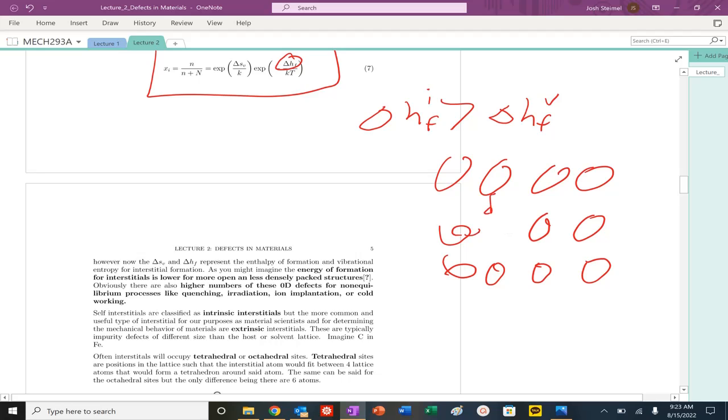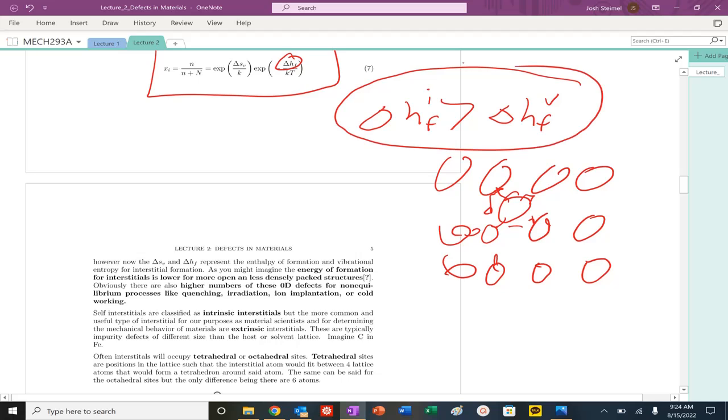So the atoms can move in and relax a little bit, if you can imagine them with springs. But if I'm putting an atom right here where it shouldn't be, it's pushing out here. So you're creating these little stress states in your system. That'll be important once we get into defect motion and migration. But it's going to be much harder to create an interstitial or self-interstitial than a vacancy.